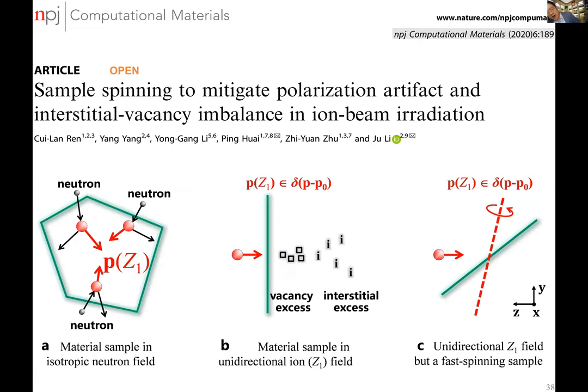And also there are artifacts. When you try to mimic neutron damage with an ion beam, there is a well-known so-called injected interstitial effect. The basic idea is that certainly you can use an ion beam to mimic neutron irradiation, but with neutrons, the momentum is isotropic. So you get the primary knock-on atom in all different directions. You create a vacancy here and some interstitial elsewhere, but it is balanced by interstitials that are over here. So overall, you don't have a net so-called polarization of vacancy versus interstitial.